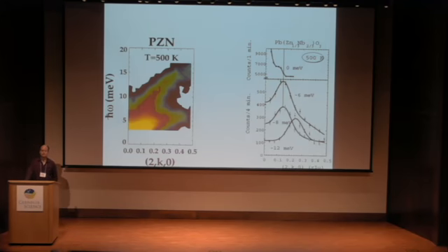So have you tried to work it out for the time of flight condition? Because when you do time of flight, you have fixed EI, and then EF is varying. So the Bragg conditions are all completely different when you're looking at the same points in Q. So how do they end up being in the same place? So you did an EI of 25 meV, right? Yeah. And you were doing EF fixed at 13.7 and your mode's at 11.5, so those two sum to roughly 25.